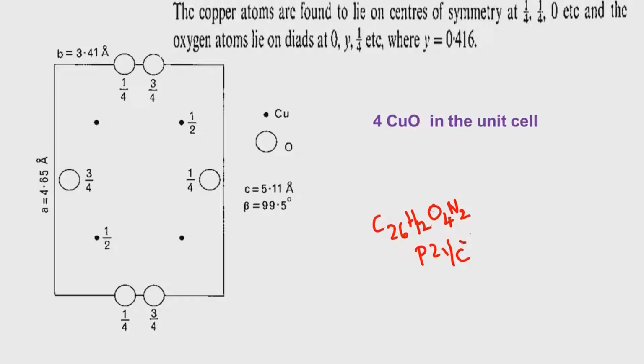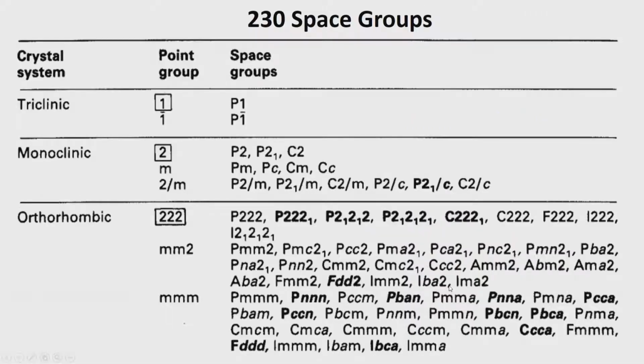This is fine. Now, we also know the positions of the special positions, and the size of the unit cell we know. So, we know the volume. We can also measure the density. So, we know the density. And since somebody said this is the molecular formula, then we can calculate the molecular weight. So, M is known, P21 by C. So, I can calculate the number of molecules, in other words the value of Z. What is the value of N we can calculate.